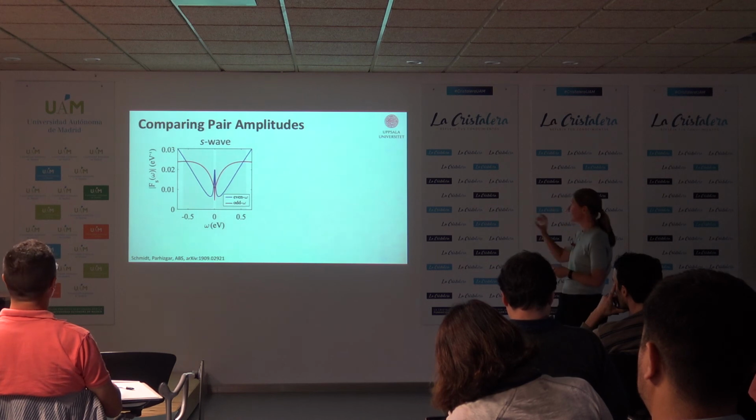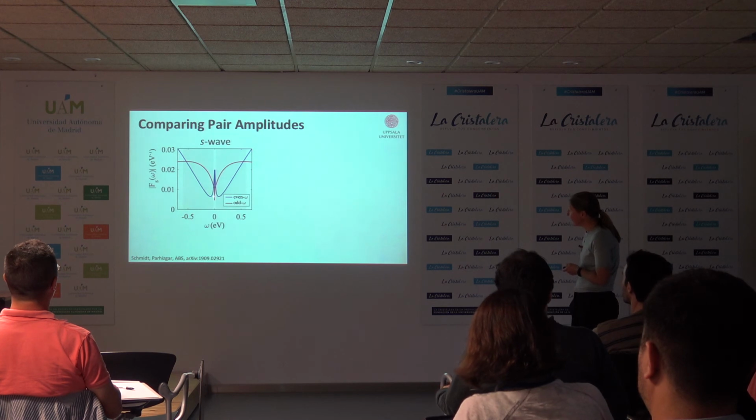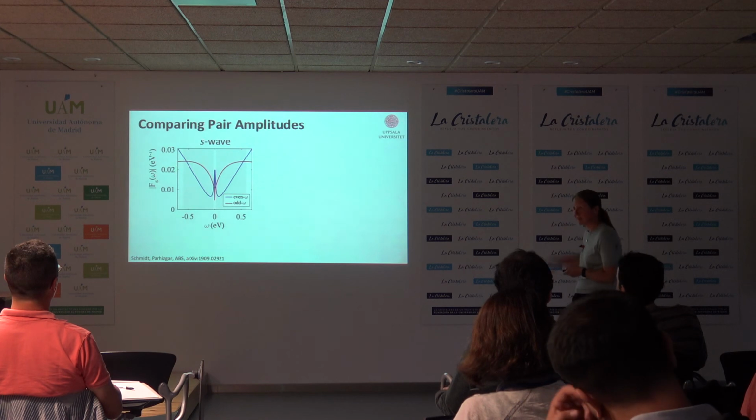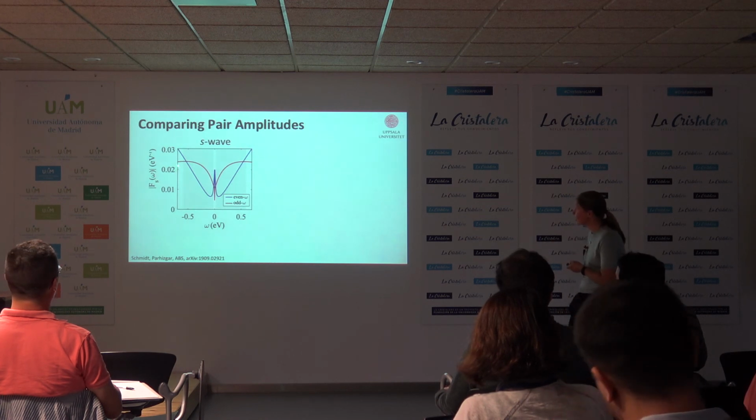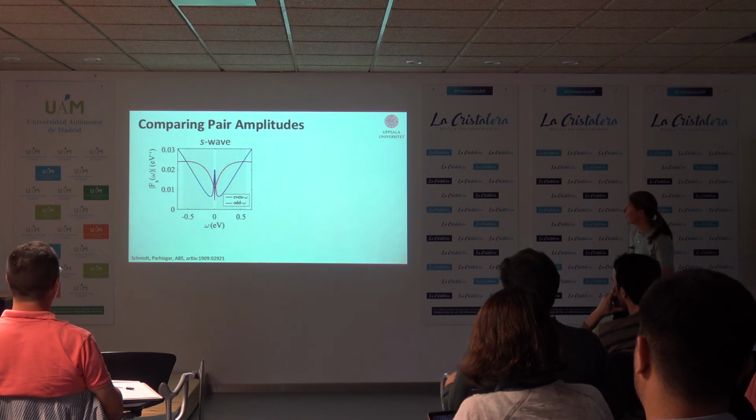So this is taking the DFT band structure for the doped TI and the experimentally relevant gap size, and it turns out that the red one is the odd frequency. This is the amplitude. Sorry, this is a magnitude. And you see in this regime here, essentially the gray regime, the odd frequency is actually bigger than the even frequency, over a rather large range of frequency.